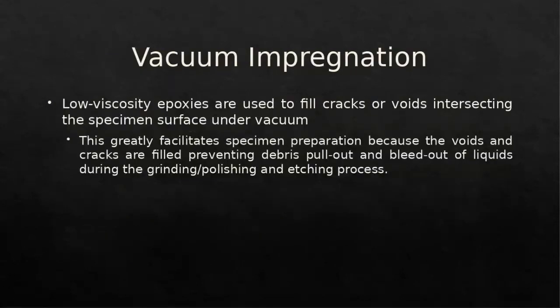Vacuum impregnation's nice, especially if you're dealing with components that are known to have a lot of surface defects, voids, just anything that's going to cause an opening. So low viscosity epoxies are used, and they can be used to fill in the cracks, the voids, areas of corrosion, anything like that. When it's under vacuum, it helps to push it in. And because now those voids are filled, it'll help you facilitate better sample preparation.